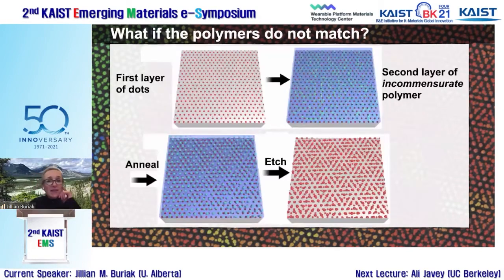Now, one thing that Chong did, again, the weightlifter, is that he said, okay, I'm going to do that first block polymer self-assembly, form the silica dots. But the second block polymer I'm going to put on there is not going to match. It's going to be different. And what's going to happen? At the time, what I thought would happen, he didn't even tell me he was doing this at the time, is that the first layer would dictate to the second layer, with a different natural native spacing. But these are soft materials. I assumed that it would force the second layer to adopt the same periodicity. It would just get thicker or something like that. That's not what it does.